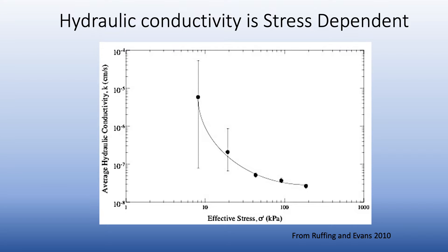The hydraulic conductivity of this material is not a single value but rather stress-dependent. As shown on this slide, the hydraulic conductivity of a soil bentonite backfill taken from a construction site in Birdsboro, Pennsylvania decreases over two orders of magnitude as stress increases over the testing range. The error bars indicate considerably more variability in hydraulic conductivity at low effective stresses.